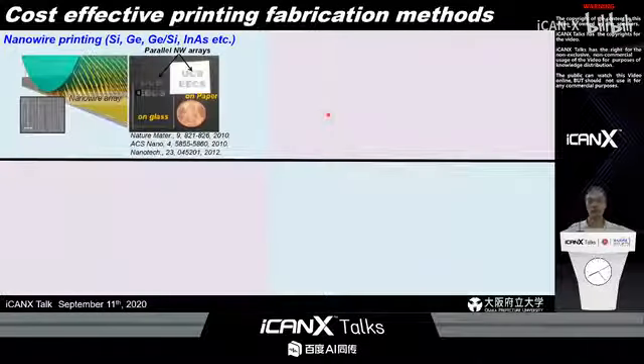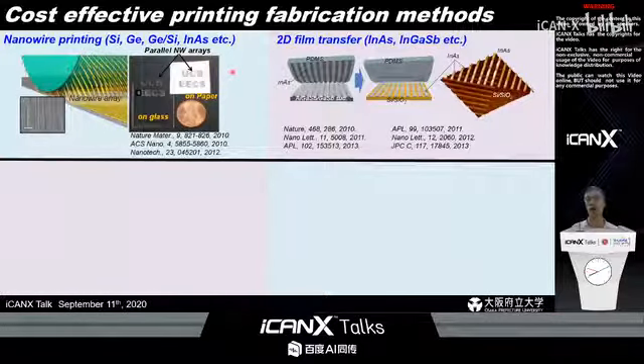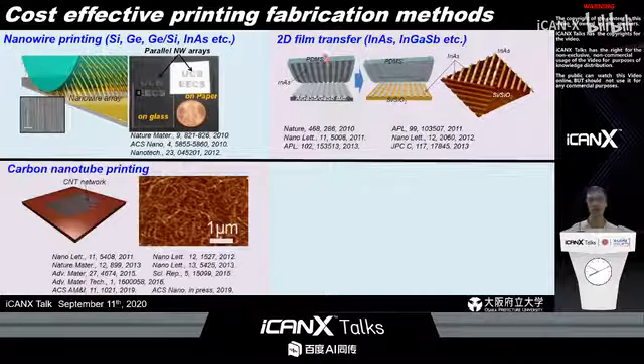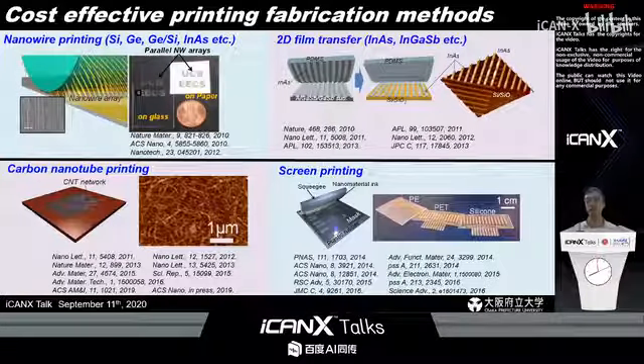To demonstrate this device, we developed several printing techniques using mainly inorganic nanomaterials. Since time is very limited, I cannot talk about the details of the mechanism, but mainly we use a van der Waals interaction between nanomaterials and flexible films. The first one is nanowire printing, the second one is III-V ultra-thin film transfer techniques, and the third one is semiconductor carbon nanotube printing to make random network structures. And the final one is screen printing by developing nanomaterial inks.